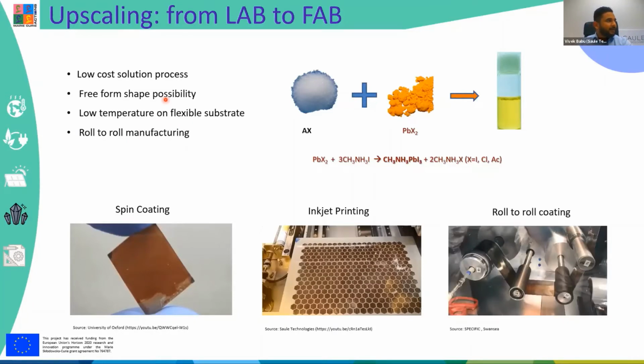And I also like to mention that these perovskite crystals can be crystallized at very low temperature. So what advantage is it? We can coat it onto flexible substrates, mostly plastic material, which can be degraded at higher temperatures. So without destroying the substrates, we can crystallize this perovskite at low temperature, and this can be utilized in